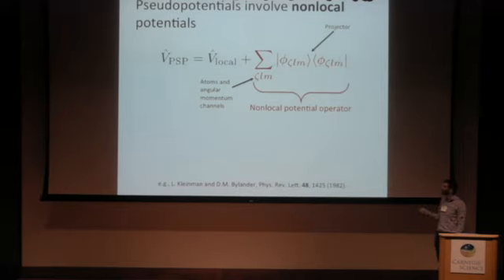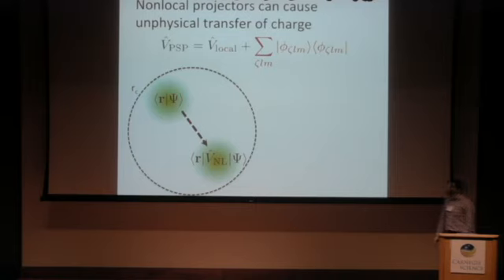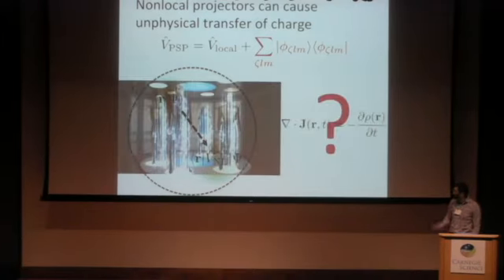So if you apply it to a wave function, you have a local operator and then a non-local operator that is in the form of this projector, in this case over angular momentum channels. And so these non-local operators cause a lot of problems for a physical interpretation of current density. The reason is if you apply a non-local operator to a wave function, you can have these unphysical and discontinuous motions of charges where charge can kind of teleport to different places within the cutoff radius. And so this kind of charge teleportation is allowed in Star Trek, but it's not allowed in physics.